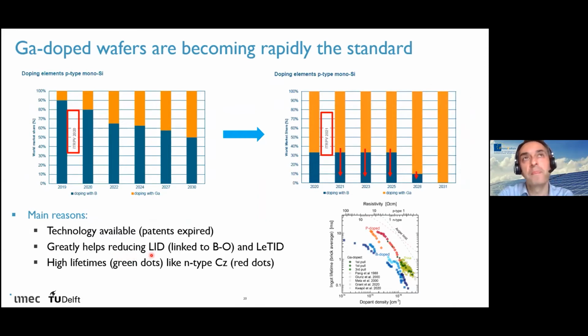So what is this? In boron doped wafers you typically have the effect that you have boron oxygen complexes, and in some cases these complexes can lead to degradation after a few years of operation. That means the efficiency of your device is reducing because the presence of boron together with oxygen creates special types of defects.